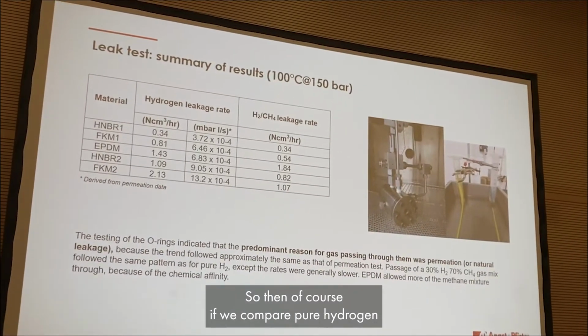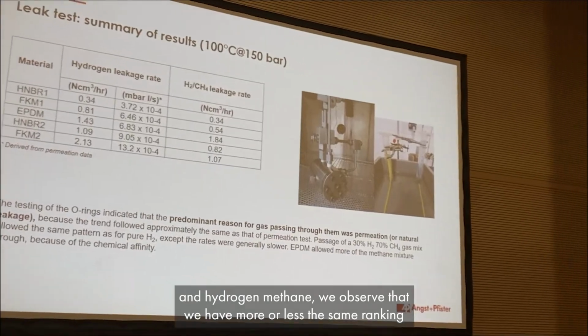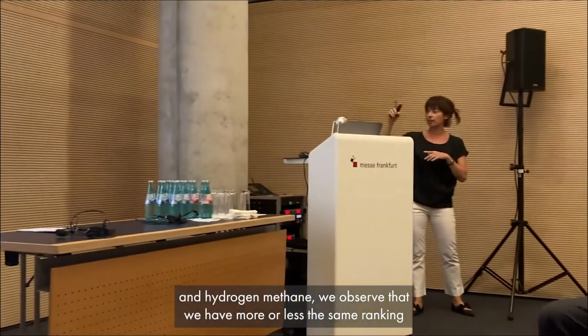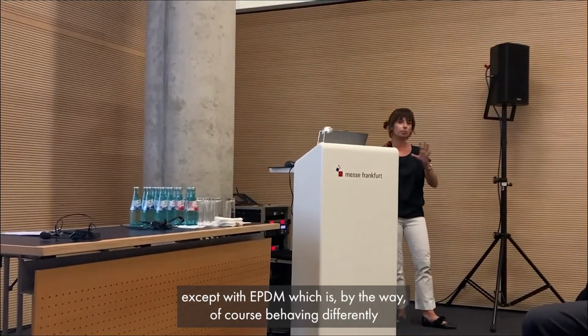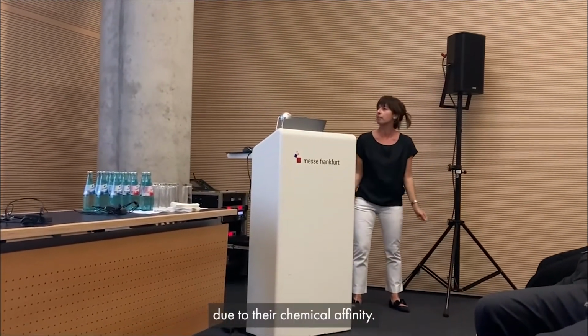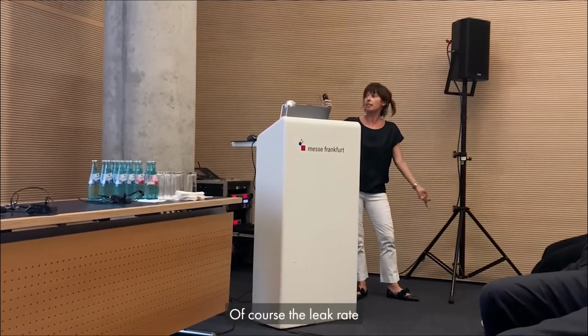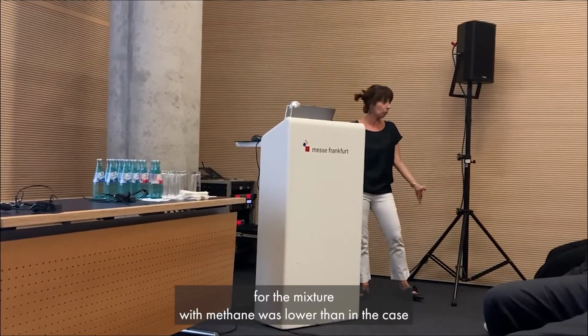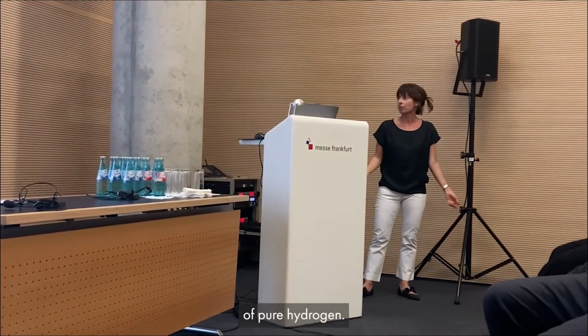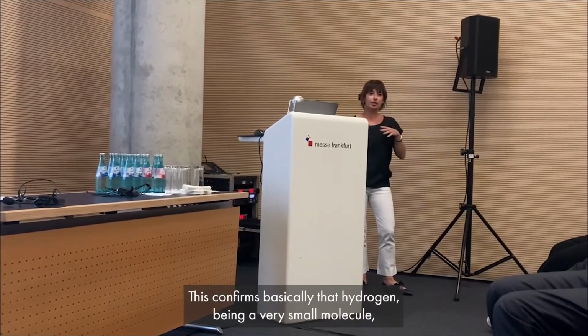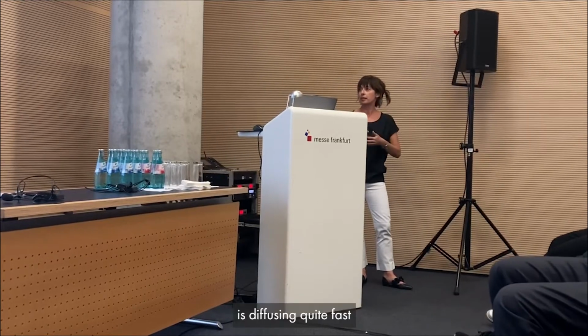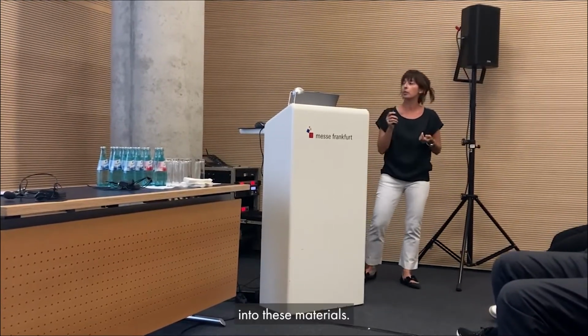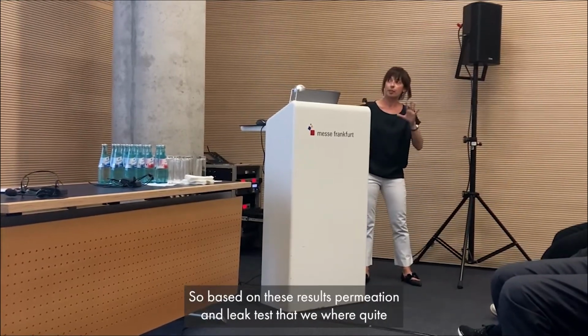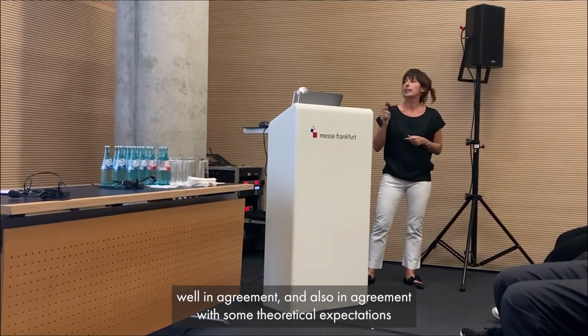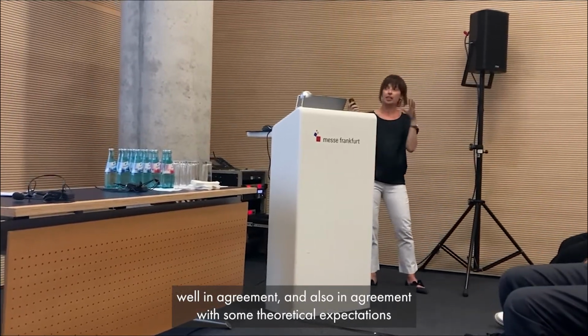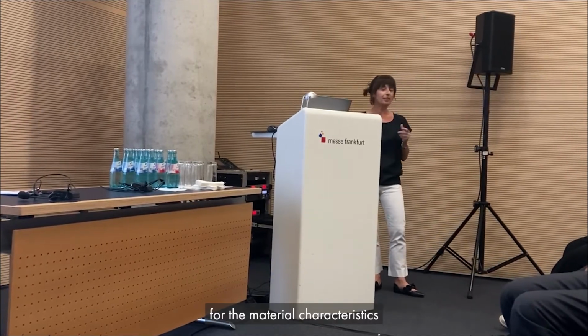So then, of course, if we compare pure hydrogen and hydrogen-methane, we observe that we have more or less the same ranking, except for EPDM, which is, by the way, of course, behaving differently with methane due to its chemical affinity. But then, of course, the leak rates for the mixture with methane were just lower than in the case of pure hydrogen. This confirms basically that hydrogen, being a very small molecule, is diffusing quite fast into these materials. So based on these results, permeation and leak tests were quite well in agreement, and in agreement with some theoretical expectations as for the material characteristics.